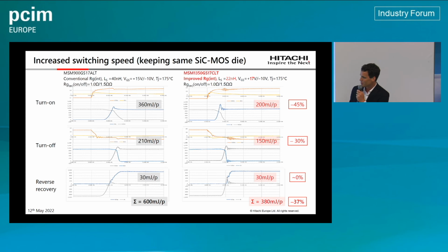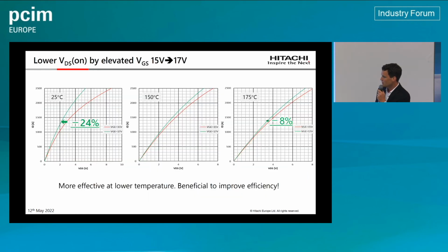So we're benchmarking the previous generation of the product to the new generation of the product. And we can see substantial reductions here in switching losses, with an overall 35 to 37% reduction. If we look at the on-state loss at high temperature, 175 degrees, we see a modest improvement of maybe 8% due to the higher gate source voltage. But as we go down to room temperature, it's maybe as high as 24% improvement in conduction loss.